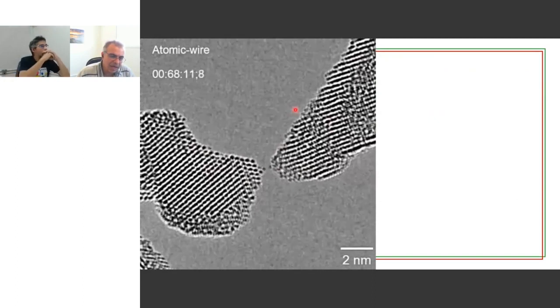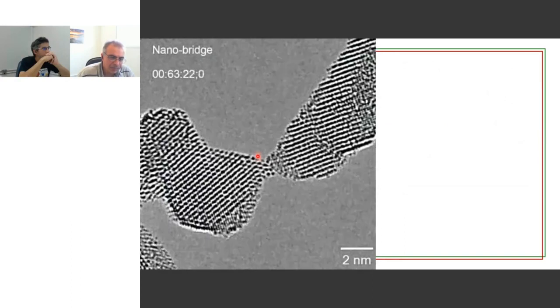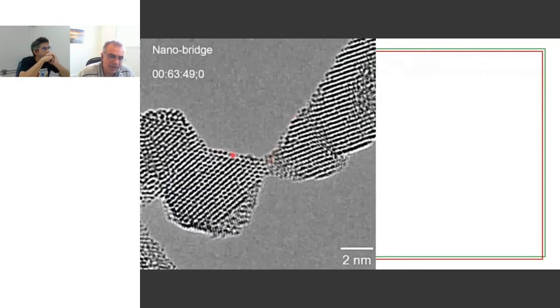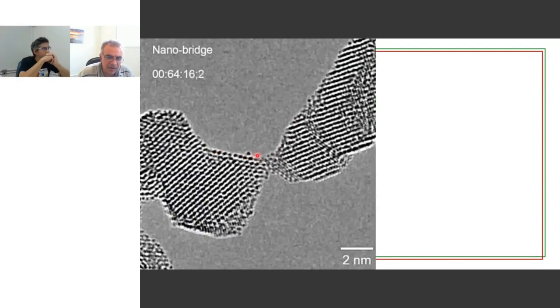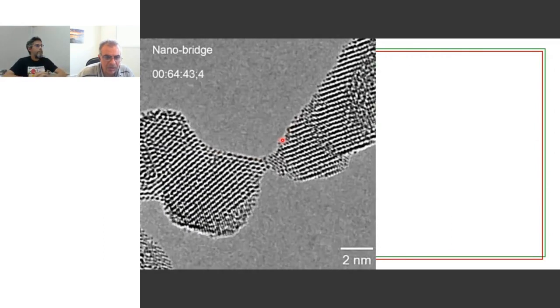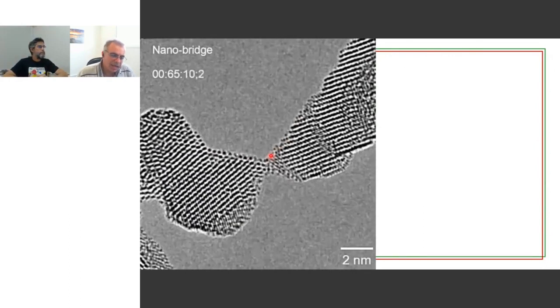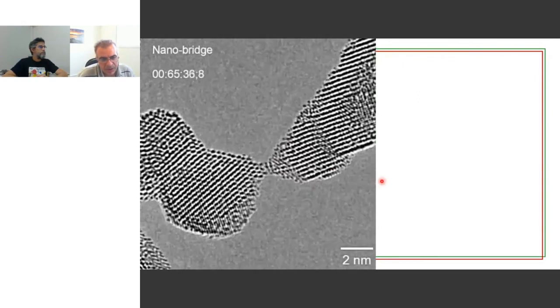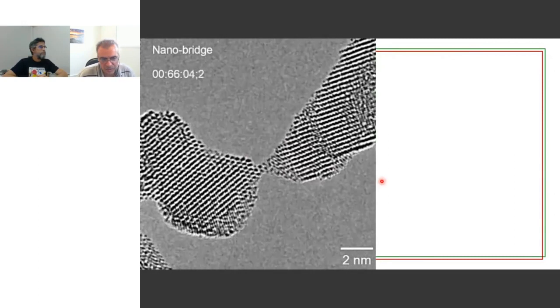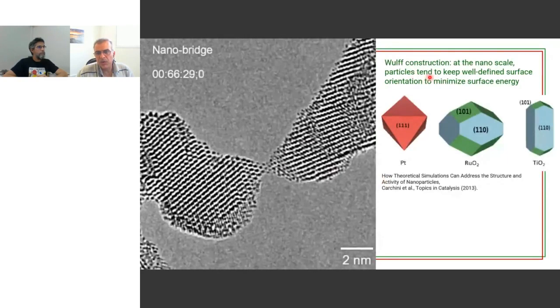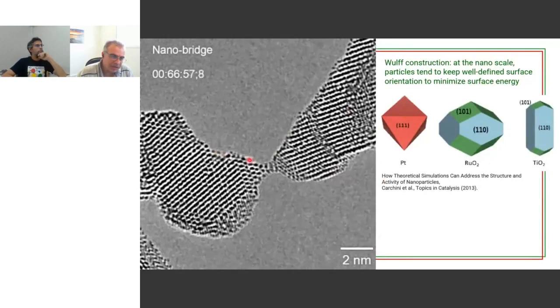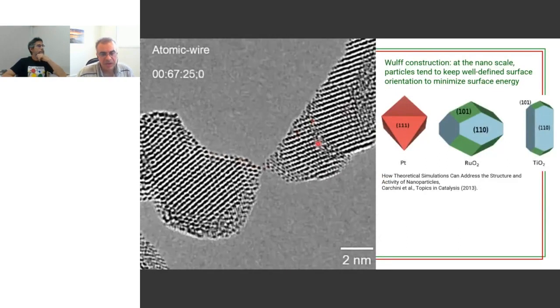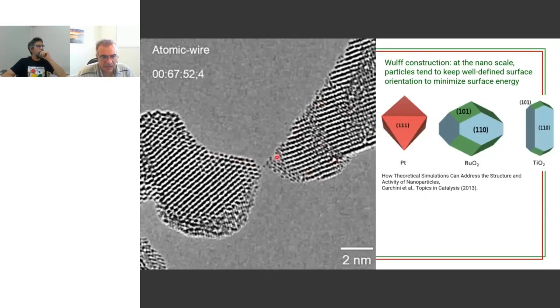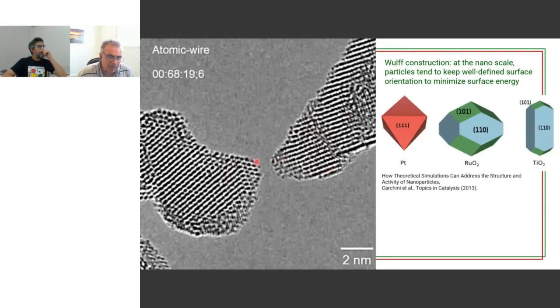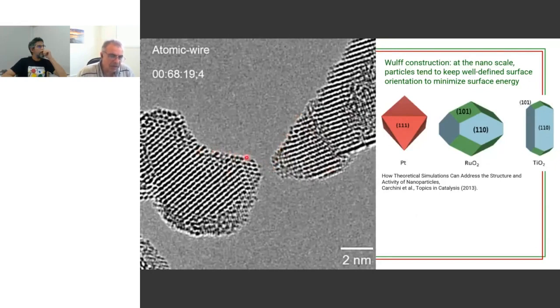The second thing, which is important, is the dihedral angle. Let me run the movie again. The dihedral angle is roughly constant. Mentally, you can imagine how you can visualize this dihedral angle here, and it remains roughly constant throughout the whole process. That's a very key point. And the reason for that is basically that nanoparticles are very different objects in comparison to macroscopic bodies. Nanoparticles tend to keep well-defined surface orientations, and this is what you see here. This is because very specific surface orientations have low surface energy, and the process happens in such a way that you are moving those two nanoparticles apart, but the system always tries to keep the same surface orientation throughout the process, okay?